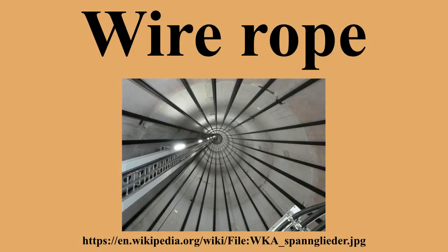Rope safety factor equals minimum breaking force FMIN over nominal rope tensile force S, at least 2.5 for simple lifting appliance. Discarding number of wire breaks. Minimum number of wire breaks on a reference rope length of 30D should be 8 for lifting appliance.